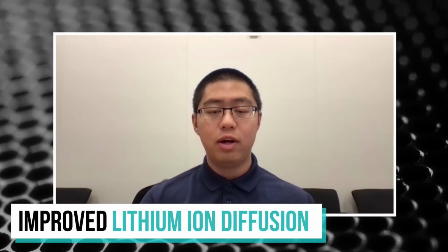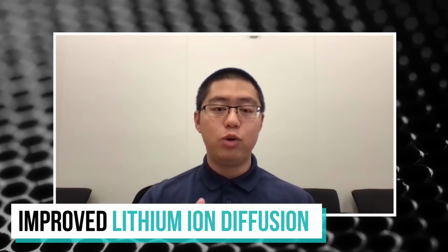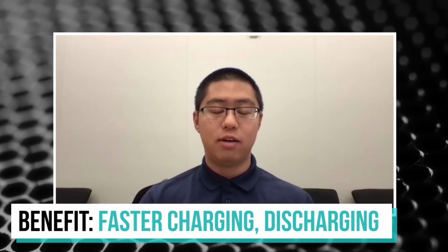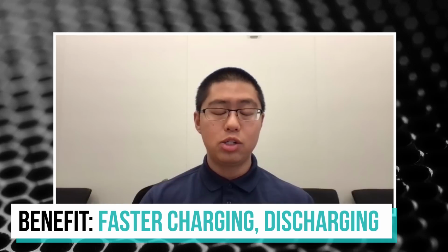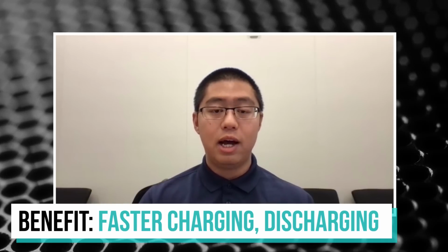Wadsley-Roth materials have a unique lattice. There are a lot of open tunnels in the lattice, which let the lithium ions diffuse through very quickly. That's the very unique thing. Also, those materials have a high operating voltage range, which can avoid the SEI and lithium plating issues. So as we mentioned before, those are the two advantages we have for those materials.